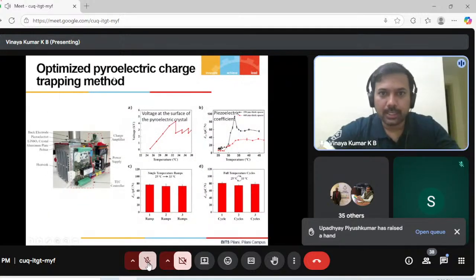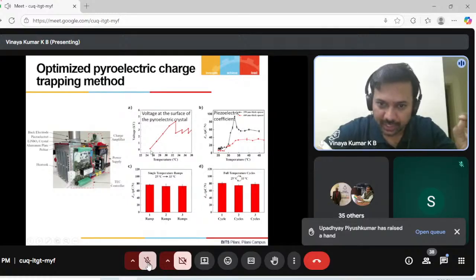Going forward, to optimize the pyroelectric charge trapping approach, this is the example I wanted to show. As you can see, the temperature where we started for the pyroelectric crystal is room temperature, like 25 degrees in an AC room, right? And then we are increasing the temperature to 26, 27, and 30. You see the surface charges. This is the surface charge we measured using a non-contact measurement tool. So it's like 3 kilovolts. Just for a change in temperature of 3 degrees, we are able to produce 3 kilovolts.